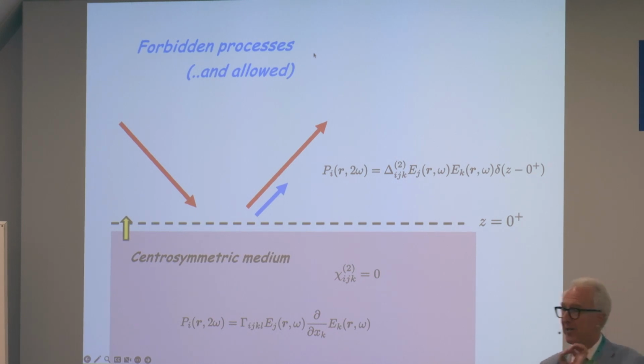Okay? And there's an interesting result: if all you can do is measure light out here, not inside the crystal, you don't have a photon detector in here, just measure light out here, you can prove that you cannot distinguish completely between, you can't pull out this delta 2 and this gamma. You can't separate these two effects. To fully separate them, you would have to be able to detect what's going on inside this crystal as well. So there are interesting subtleties with these forbidden processes.